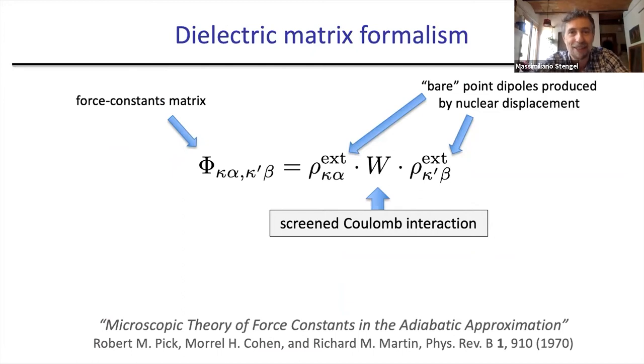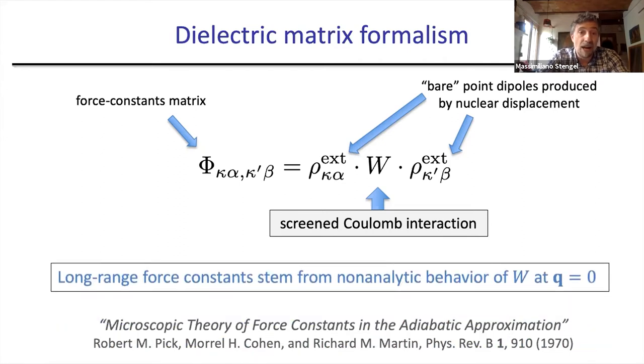To put this topic in a theoretical framework, I'll use the approach of the 70s — the dielectric matrix formalism. To understand why we have long-range force constants, let me write the force constant matrix as the interaction between two point charges displaced within the crystal, interacting via the screened Coulomb interaction. This is a static screened Coulomb interaction because we operate within the adiabatic approximation. The long-range force constants essentially stem from the non-analytic behavior of the screened Coulomb interaction W — this is the main focus of this talk.